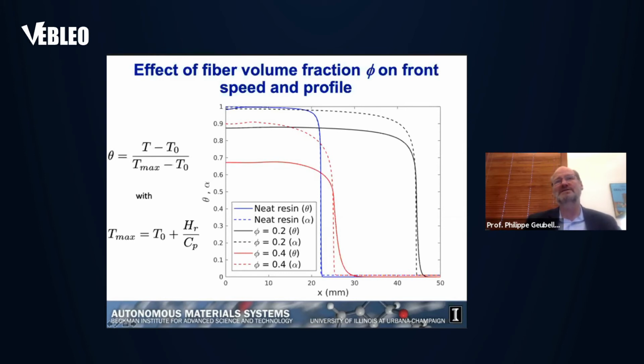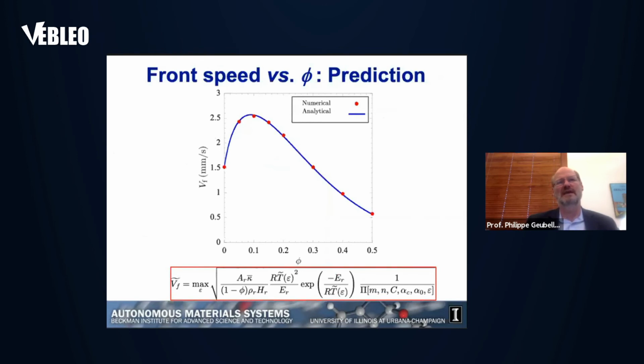And that's obviously something that is important because the speed at which the front will propagate is a key component of the manufacturing process. And actually, we studied this both numerically, which are the red symbols. So this is the speed of the front as a function of the fiber volume fraction. And we also developed an analytical expression for this front speed as a function of the fiber volume fraction. And you can see a very good match between the two. And so what we observe is that it first increases, reaches a maximum, and then starts to decrease, right?